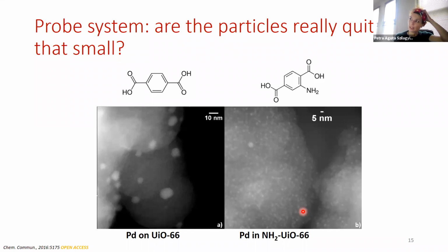In this case, we can do it by using the functional groups to help anchoring the particle itself in. We know what temperature the palladium nitrogen bond is broken. So one thing that I'd like to look at is to really heat treat it further and see if we can get rid of all the single atoms while keeping the clusters. But this is something that we only recently found out, so I haven't done it yet. That's the next stage.